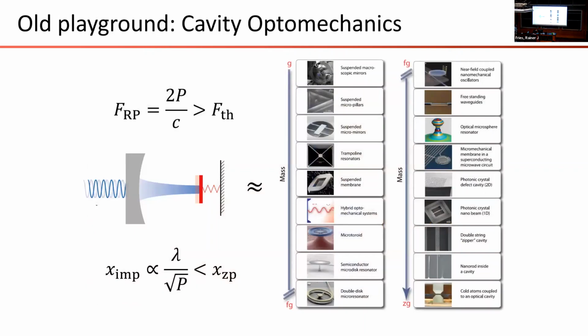So our playground traditionally for these types of mechanical resonators is a field called cavity optomechanics, where we take mechanical oscillators and couple them to optical cavities, and then we use radiation pressure forces to manipulate them. One reason for this is simply that it's interesting to see radiation pressure forces. They're typically very weak. It's hard to see them. However, another interesting reason is that you can make very sensitive displacement measurements of mechanical oscillators in optical cavities. And if you can get in the regime where radiation pressure force starts to dominate the dynamics of the mechanical oscillator, you can do interesting things like laser cooling.